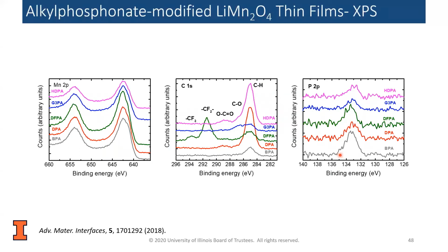And so here's just some quick XPS to demonstrate that when we change the length of, for example, the hydrocarbon type SAMs, we are actually increasing the carbon signal. Then we see when we have the fluorinated carbon, we are seeing the indication of the fluorine. And then for the polyether, we actually didn't see much.